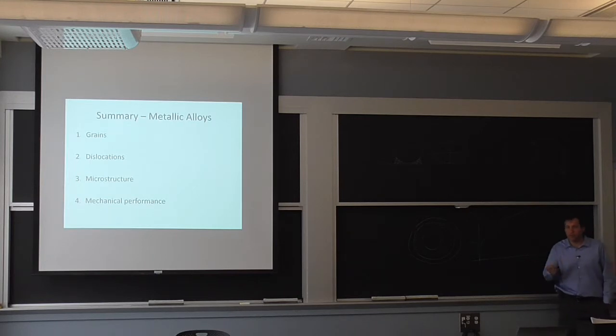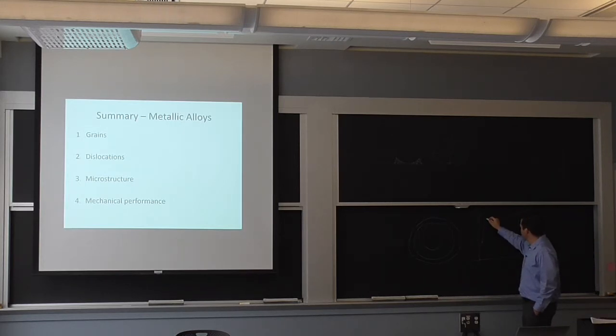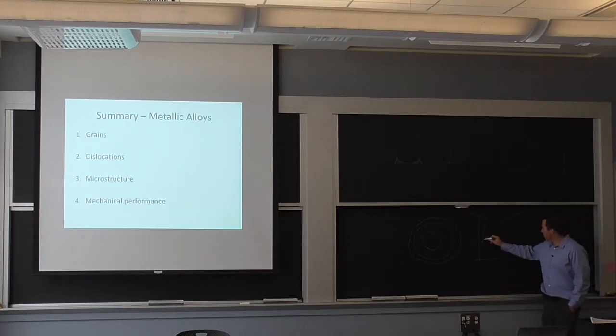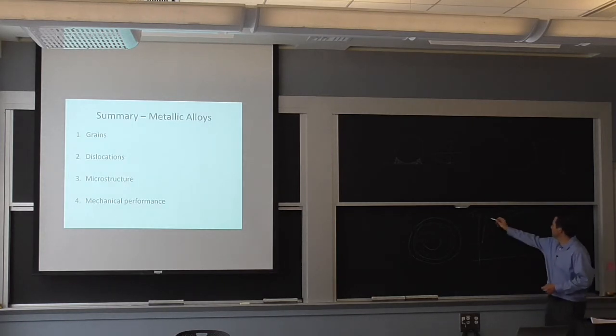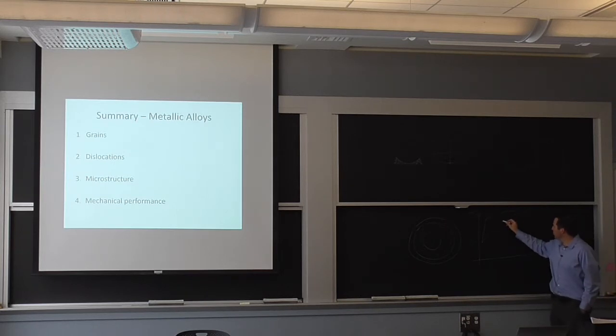If we have strain and stress — I'm just drawing some stress-strain curves for our discussion. If I take annealed aluminum, it has a very low strength, say 5 KSI, and it will typically increase its strength a lot when I'm deforming it. The reason is it had very little dislocation in the beginning. If I take another aluminum alloy that was cold worked, it's essentially elastic for twice the height, then it's not going to harden as much when I reach plasticity. This is really the way it works: if I just pre-deform it, I'm eliminating this strain hardening behavior and starting from a higher point.